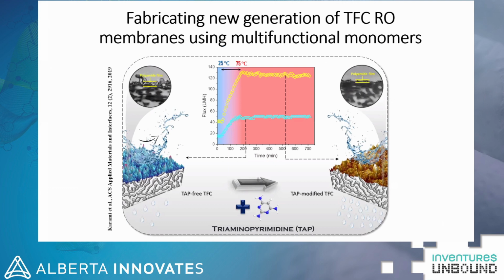In another study, we didn't add any nanoparticles to the top layer. What exactly we did here, we tried to tune the chemistry of the polyamide layer by adding another multifunctional monomer to the IP reaction. We used triaminopyrimidine, or TAP, which has three NH2 groups that can contribute to the reaction. So our hypothesis is that by having more of those functional groups, you have more reaction and you have more cross-linked density of the polyamide layer, and therefore we have a higher thermal stability of the TFC membrane.